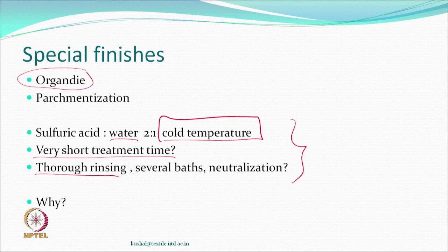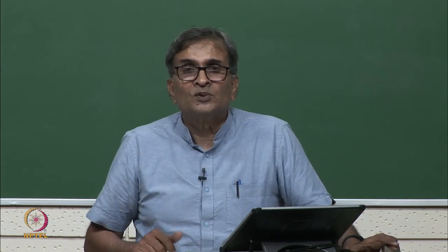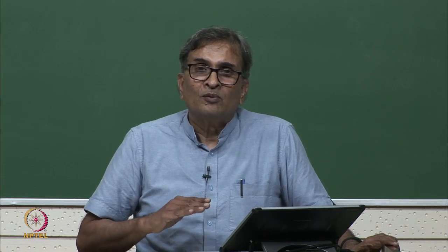Why did this happen? Where did it happen? What do you think has happened? Sulfuric acid. So obviously, in the short period, the sulfuric acid is going to act on the surface. Okay? If it acts on a surface, then what happens? Some of the cellulose may dissolve, but it doesn't get time to get out into solution. And the moment you put it in the washing liquor, this so-called soluble cellulose, which may have broken down to relatively smaller molecules but still very long molecules, immediately coagulates back. And if you see this happening, cellulose is binding cellulose itself.